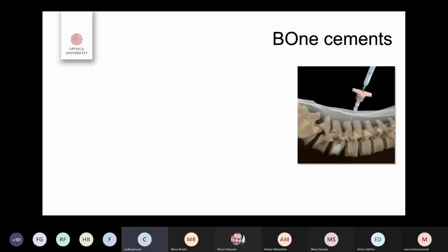After my PhD thesis, I actually continued to work with PMMA-based bone cements, but now in a different application, so in the spine. And here, of course, the cements were taken from the application in the joints and used instead in the spine. In a minimally invasive procedure, we inject the cement, it hardens in place and stabilizes osteoporotic fractures. And this is a very efficient pain relief method, but what we saw was that in many cases, you got an increased amount of additional fractures next to the treated vertebrae. And one of the reasons for this was believed to be the high stiffness of the bone cement.